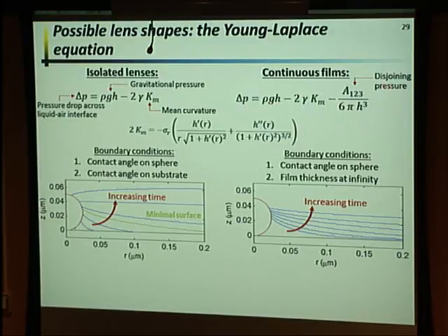We're adding in another term here, and this is a disjoining pressure. So this becomes important when you have very thin films. You notice this H is the thickness of the film. When this H gets around the 10 nanometer level, this term starts to become significant. So really, everything on this side is you're adding up different force terms. And it's OK to add different force terms if those terms are significant. So you have to make sure you're capturing everything that's significant.